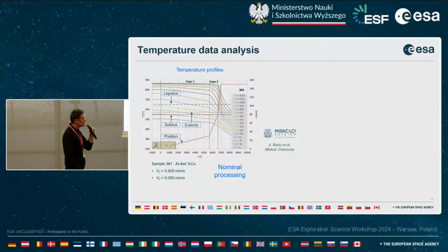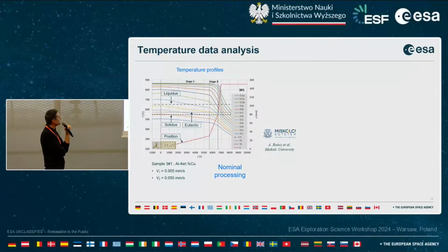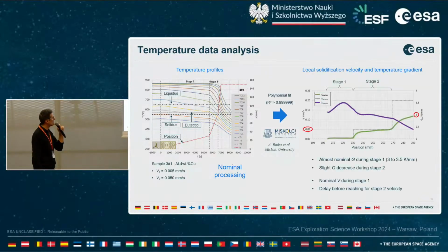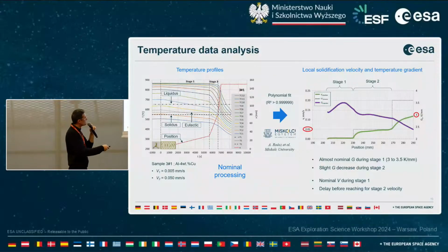Here you can see in this beautiful plot the temperature. It's a bit difficult to read, so just keep in mind that the processing was nominal for all the experiments. And colleagues from the University of Miskolc have been studying these temperatures in detail to retrieve the local temperature gradient at the solid-liquid interface, and also the growth velocity based on these measurements. And what was obtained was that the temperature gradient varied a little bit, so it was okay.